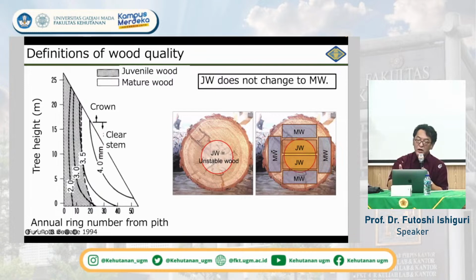So what does it mean? It means that if we cut structural lumber that needs strength properties from the middle portion, it consists of juvenile wood, so it shows a lower Young's modulus and not so good dimensional stability. But even in the same log, if we cut the lumber from the outside, consisting of mature wood, this lumber shows a higher Young's modulus than those lumbers. So even in one tree, one log, it is quite different. So we have to consider the juvenile wood and mature wood concept.